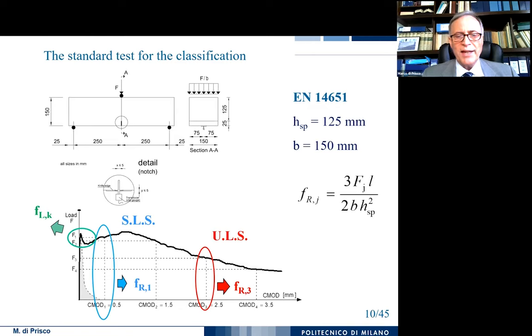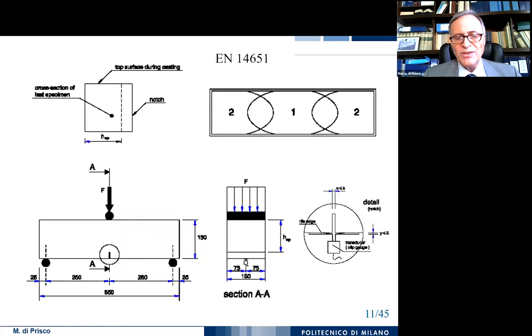So what happens? Essentially, in order to compute this, we need to compute the flexural residual strengths according to the classical modulus computed in elasticity. So we have to compute the bending moment, and we have to divide it by the section modulus. In this way, we characterize our material at 3 points: at cracking, for a crack mouth opening displacement of 0.5 millimeter, and for a CMOD equal to 2.5 millimeter. The cracking point is good to know in order to know the behavior close to the cracking. The 0.5 is correlated to the serviceability limit states, and finally 2.5 is correlated to the ultimate limit state.